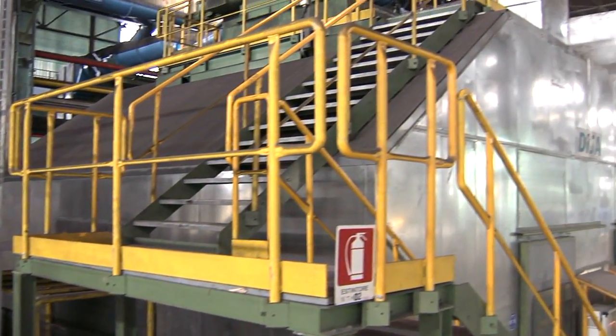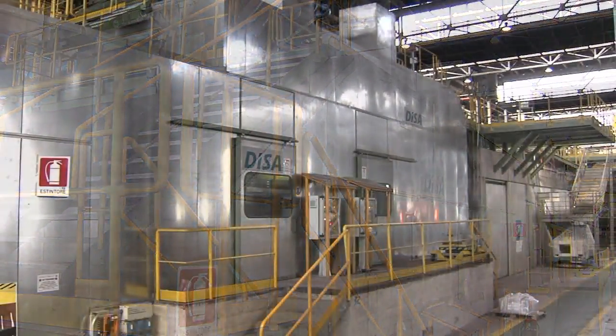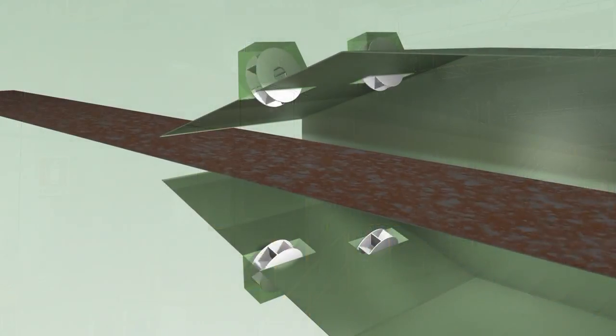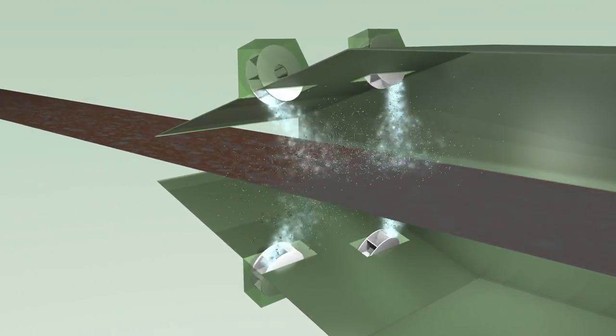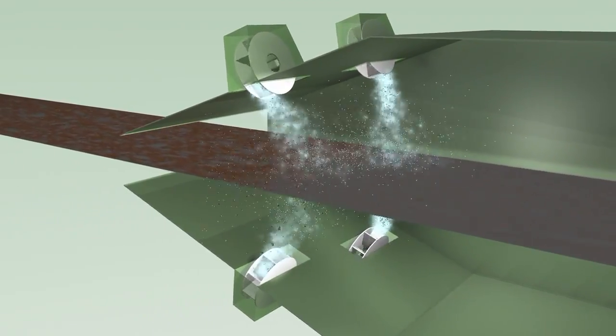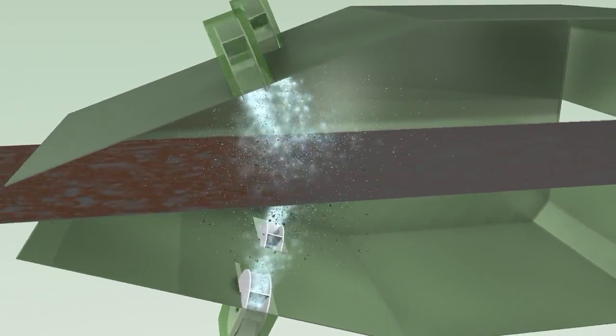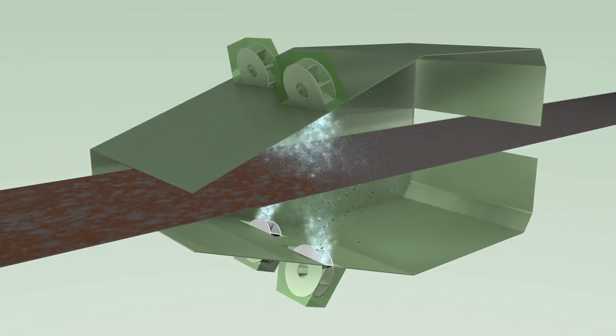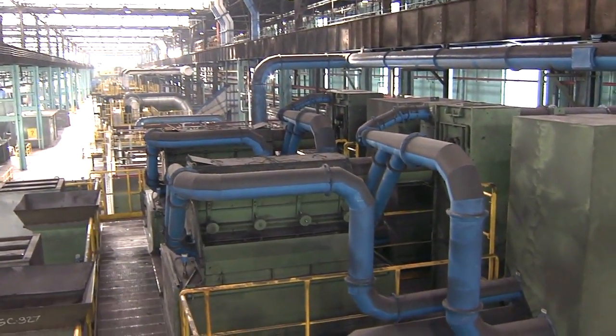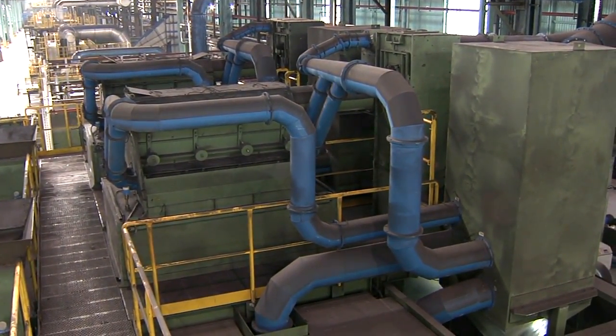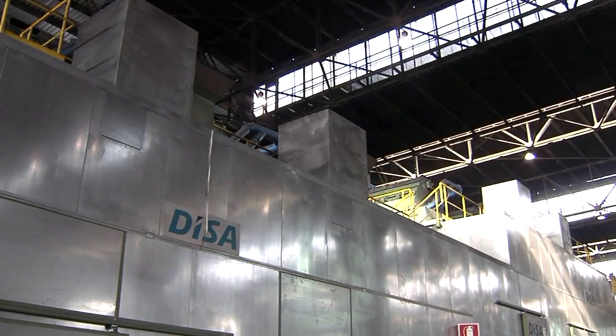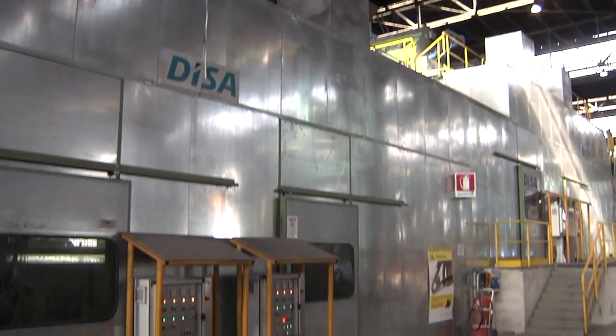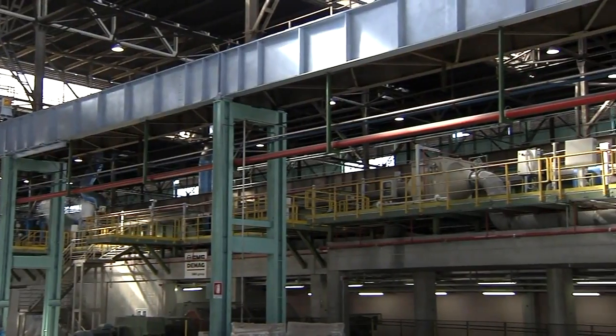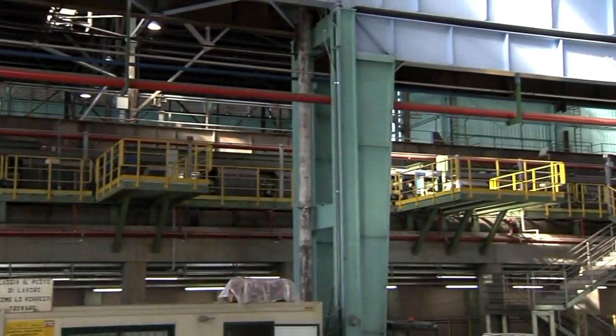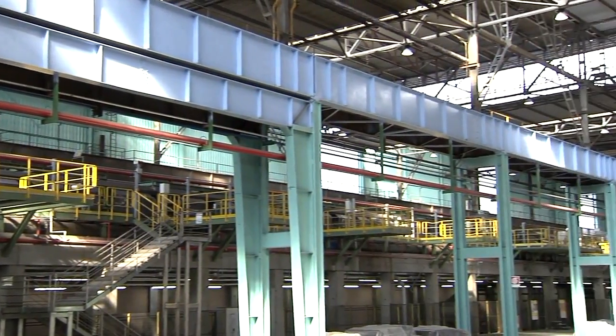The blast cleaner with 4 blasting booths. Shot blasting techniques are used to clean the scale off the strip surface with metal shot. Up to 50% of the scale can already be removed by this. Afterwards, scale and blasting medium are separated by a filter unit, with the medium being returned to the process. The 150-meter-long pickling section now follows. Process speed 80 meters per minute.